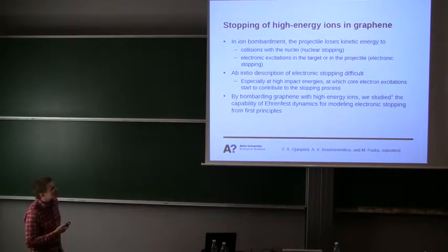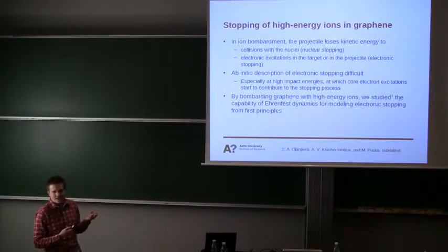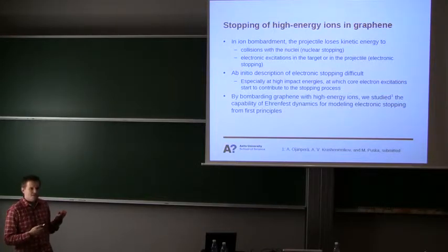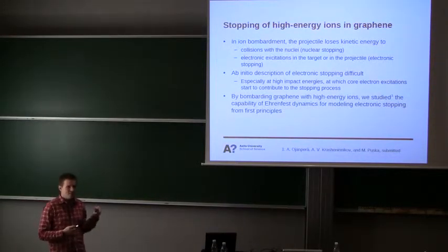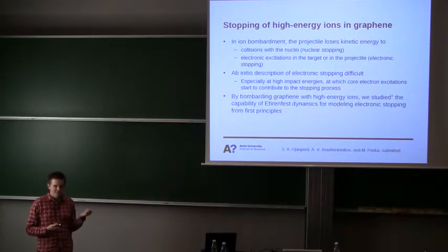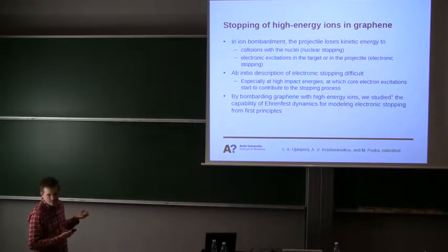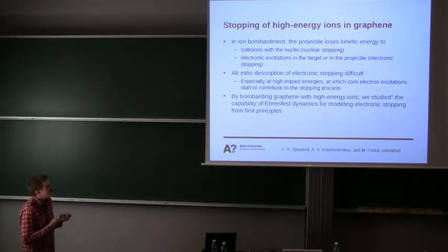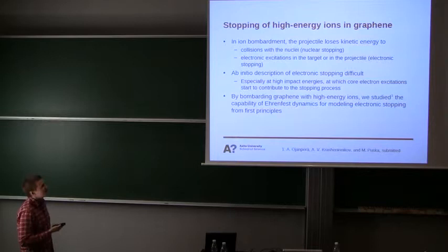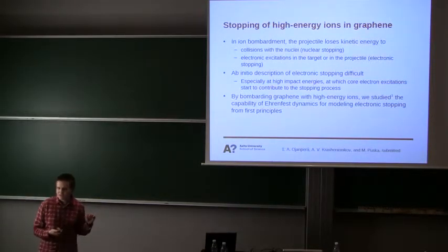Okay, moving on to my next application, which is electronic stopping of high energy ions in graphene. Here the idea is that when we bombard materials with ions, the projectile can lose energy either to the nuclei of the target or to the electrons. The latter process is interesting because it's non-adiabatic, so to study that, we need Ehrenfest dynamics. In general, the electron stopping process is difficult to describe, but here we show that Ehrenfest dynamics can provide just that.